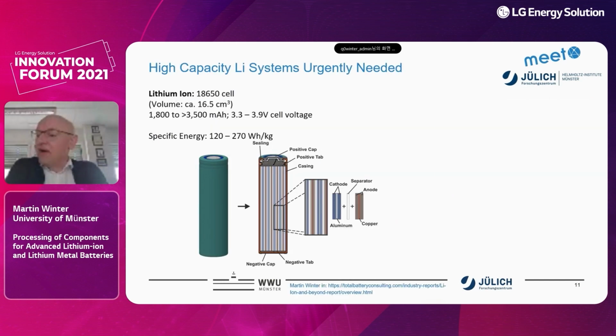So maybe you are not aware of it, but lithium-ion cells really are high-energy cells because of their high voltage. Typically, a lithium-ion 18650 cell has, for a very high power battery, maybe 1800 milliampere hour, and for a high energy cell, more than 3500 milliampere hour at a cell voltage, depending on the cathode, of 3.3 to 3.9 volt. This gives us specific energies presently of 120 for high power, or 270 watt hour per kilogram for high energy, for an 18650 cell with a certain volume.